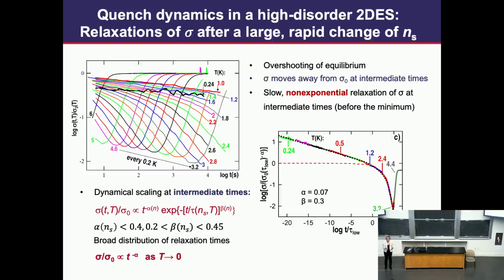In other words, there is no characteristic time scale. You have power law relaxation, and all of these are typically found in glasses. It means we have a very broad distribution of characteristic relaxation times in the system.